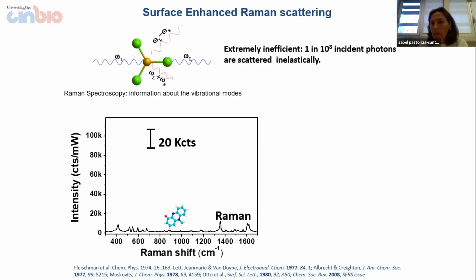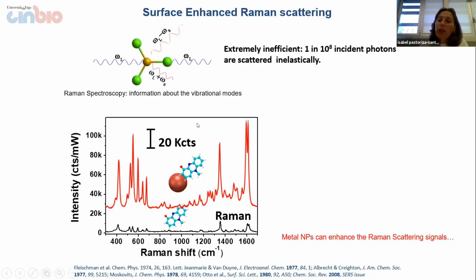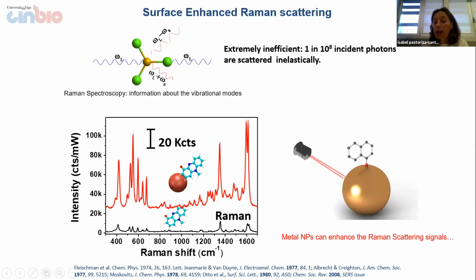But last century, in the 70s, it was found by Fleischmann that the vibrational modes of pyridine were enhanced when the pyridine was adsorbed on a rough silver film. Fleischmann explained that effect due to the large adsorption of the molecules on the silver film. Nevertheless, it was later found by Jeanmaire and Van Duyne, and Albrecht and Creighton, that there are two mechanisms involved in the Raman scattering. One is related to the near electromagnetic fields generated around the nanoparticles when they are excited, and another is the chemical mechanism, which is related to electron transfer occurring between the molecule and the metal.